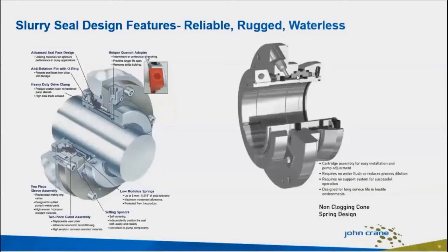John Crane employs a lot of design features in our slurry seals that are specifically meant to give our seals the reliability and ruggedness required by unique mining conditions. Seal face designs are optimized to handle a lot of abuse in rough operating conditions. We use premium grade silicon carbide face material as a standard, or an advanced silicon carbide that uses controlled density material that is very good at scavenging water out of the slurry to keep the faces lubricated in poor conditions. Heavy-duty drive mechanisms give the positive torque transmission that these demanding applications require.